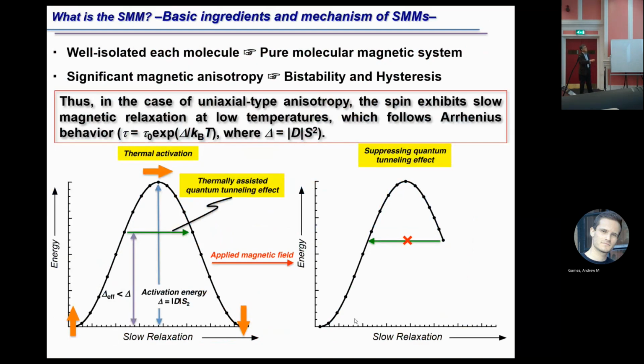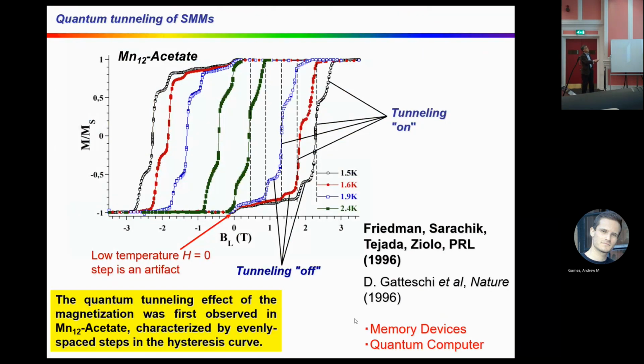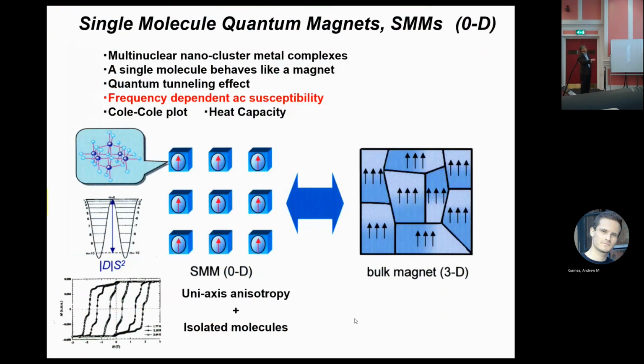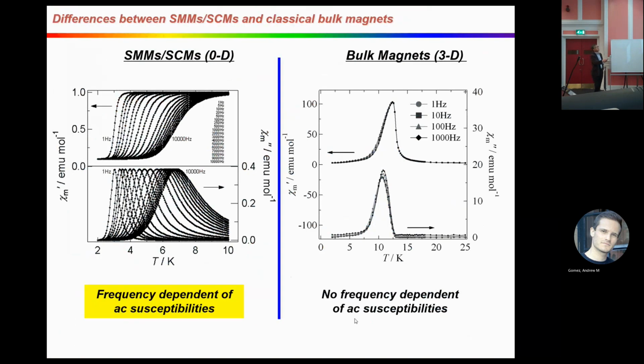So then this is another view. This is a potential barrier below the blocking temperature, upstream or downstream. And this is thermal relaxation, and quantum noise and quantum tunneling occur. So this is thermal relaxation, hysteresis, and you can see the step. This is the quantum tunneling. So this is available for memory devices and quantum computers. So, frequency dependency in AC susceptibility. In the classical magnet, the three-dimensional magnet, we shift from 1 Hz to 1000 Hz, no frequency dependency. However, in the single molecule magnet, zero-dimensional, there is a very beautiful frequency dependency, perfectly defined.